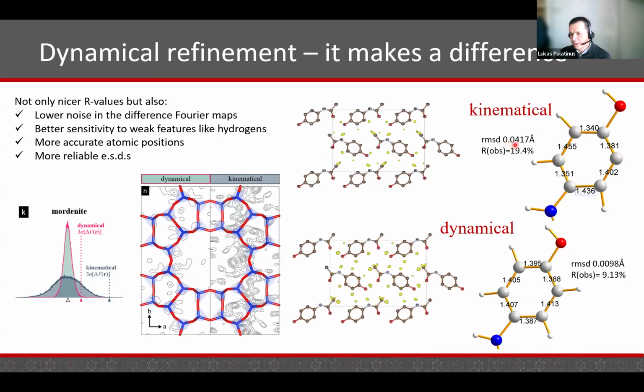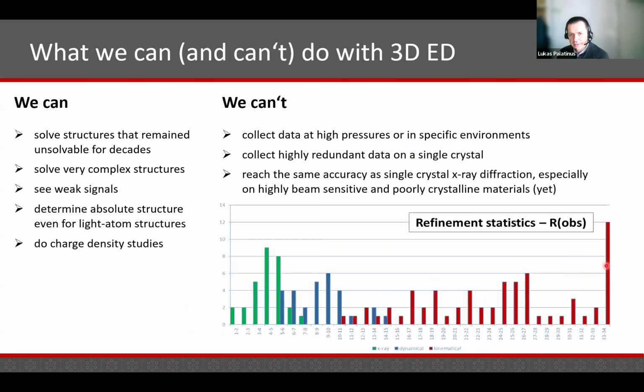So the root mean square deviation is about 0.04 angstroms, which is relatively large. It is comparable to the difference between a single bond and a double bond. So it may cause troubles in chemical interpretation. When we move to dynamical, the root mean square deviation drops down to just about 0.01, so significantly better. So with this introduction, let's move to the examples.